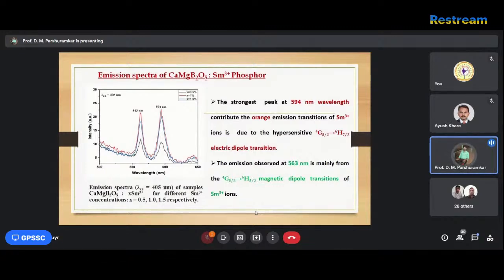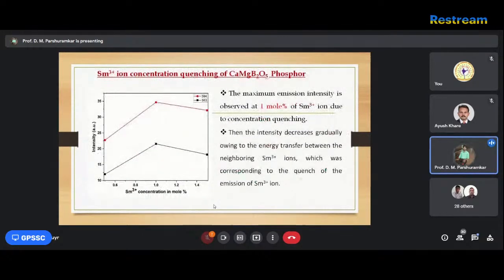Then another emission peak is observed at 563 nanometer, mainly from the 4G5/2 to 6H5/2 magnetic dipole transition of the prepared CaMgB2O5 Sm3+ phosphor. We analyzed the concentration of Sm3+ as 0.5, 1 and 1.5 respectively, and we see that for 1 mole percent we got the maximum intensity in the emission spectrum. Then we studied the concentration quenching for this CaMgB2O5 phosphor. The concentration quenching suggests that for 1 mole percent of Sm3+ we got the maximum intensity.